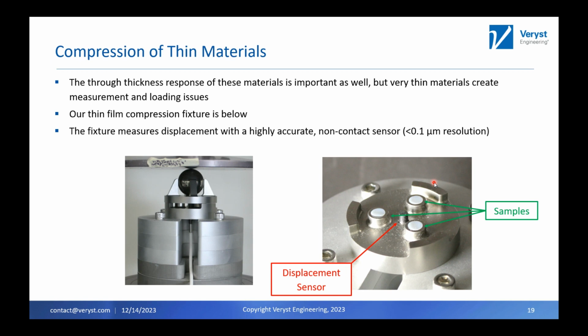The other thing that we've done, which we didn't show here, in some cases when we want to go really slow, is there's more to this fixture where it gets put on this large structure with the big spring. Essentially we have a spring in series, and we tune the spring based on the size of the samples so that the spring gets most of the deformation. That way you're lowering the deformation rate on the sample, but the force is obviously the same. So we've done that as well, in a similar way, to go even slower.